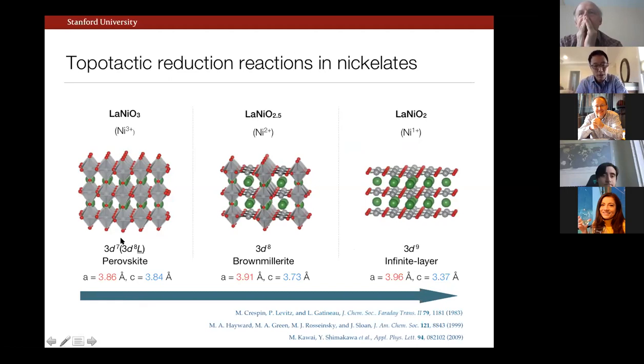But at least qualitatively, one of the things you may have to worry about, and again, this is work from Professor Shimakawa and colleagues, is that lanthanum nickelate is a bit closer to that regime. What they find is that when they reduce their films, it goes from this to this to this, but actually the final stage is that the planes stand up perpendicular to the interface. So qualitatively, I understand this to be all driven by the energetics of accommodating that strain state.